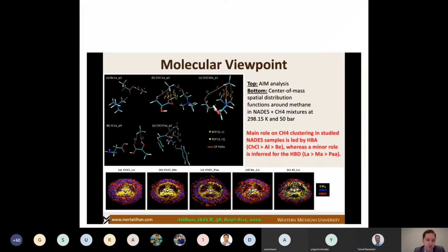So density functional theory really gives us very good insight into the material. Basically, we create our models. We use either Siesta, Gaussian, or Orca DFT codes. Then we move the calculated simulation results to the Atoms in Molecules platform to see exactly which part of the gas molecule is interacting heavily with which part of the hydrogen bond acceptor or hydrogen bond donor, because experiments don't tell anything about these things.